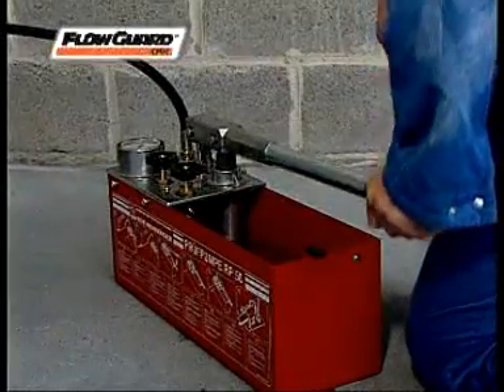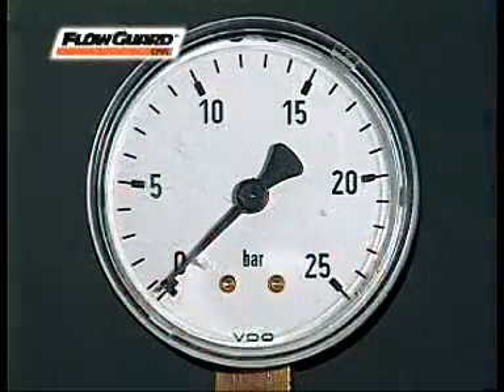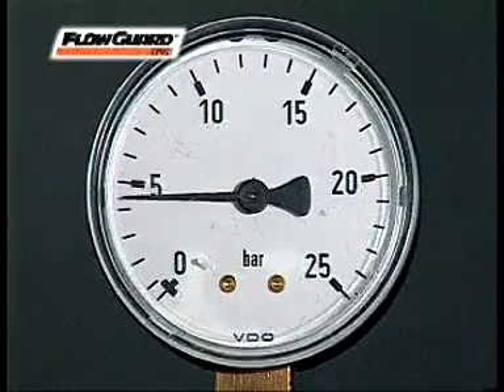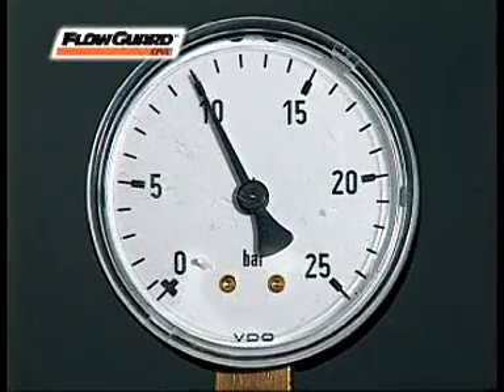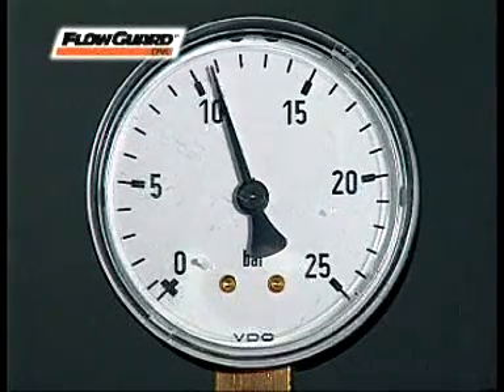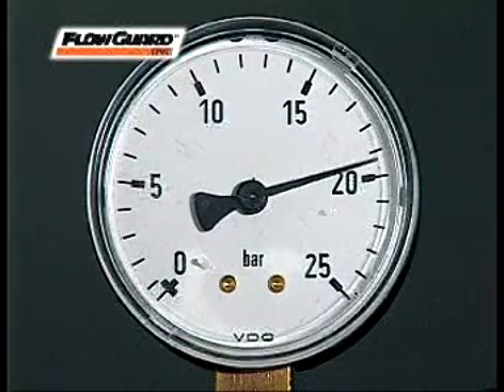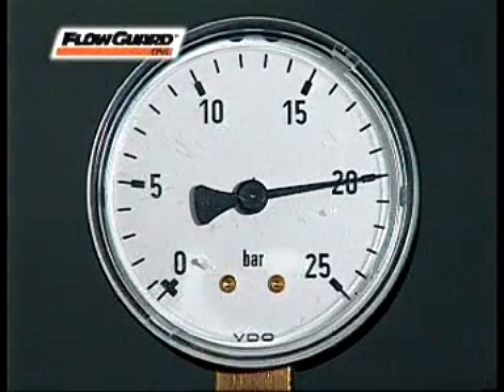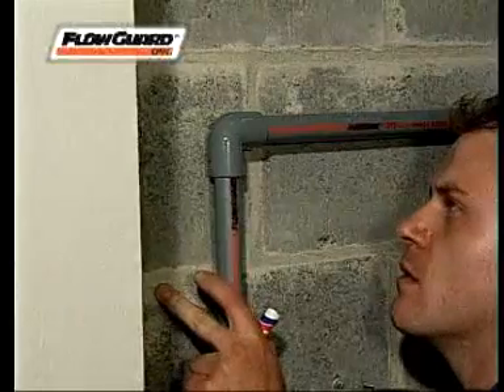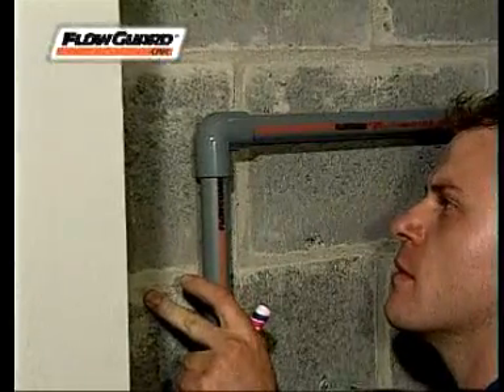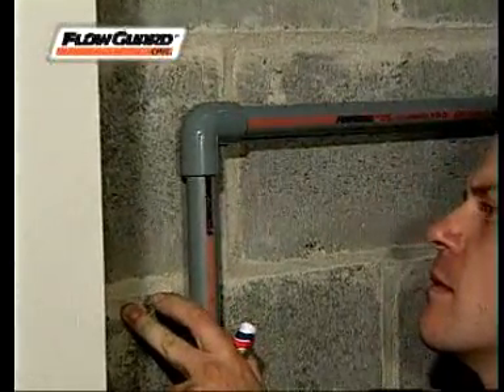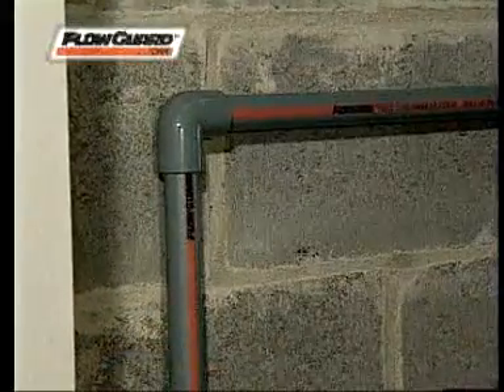The system should be hydrostatically tested with at least 10 bar for 1 hour. The pressure may need to be higher depending on the local building codes and the pressure rating of the pipe being used. If you find any leaks, mark them, drain the system, cut the damaged sections out and replace them.